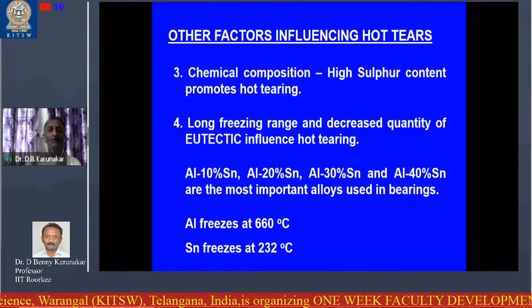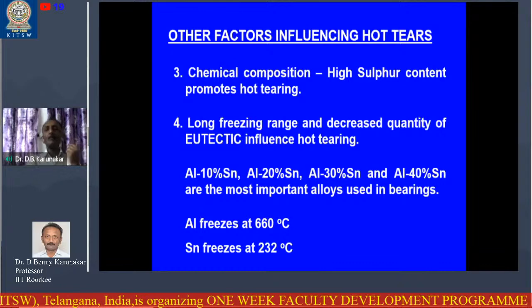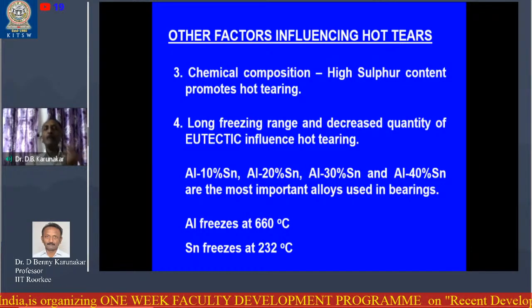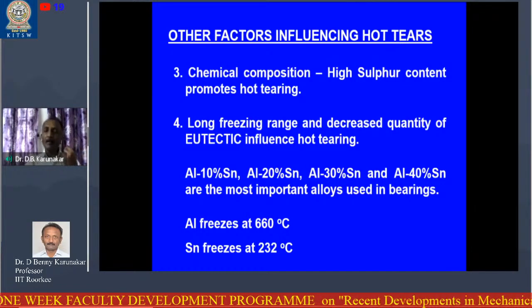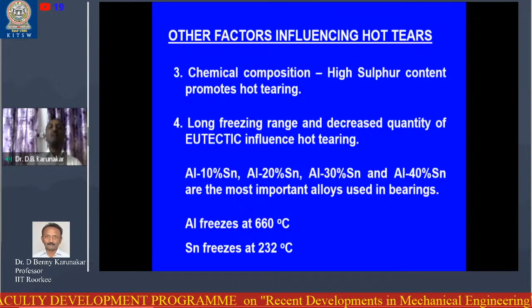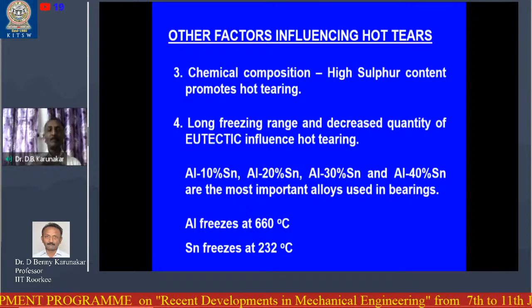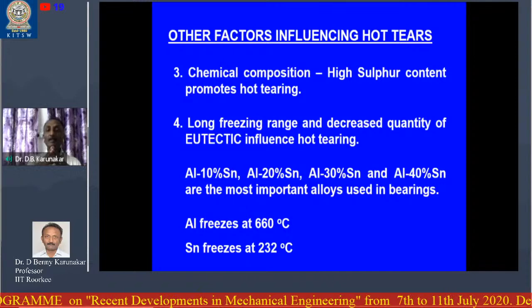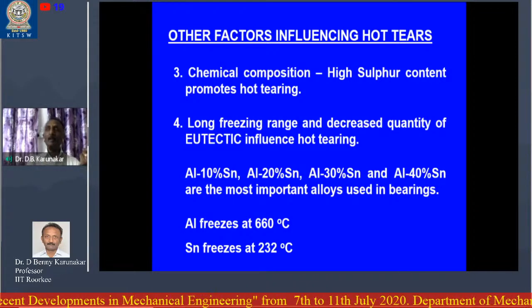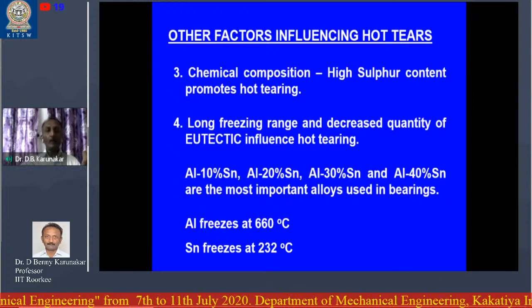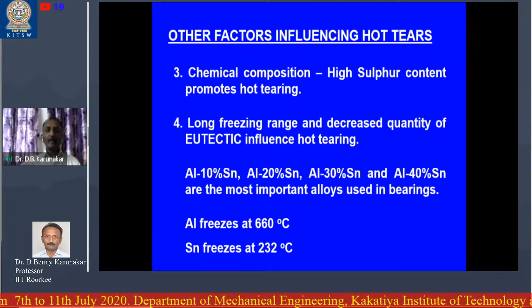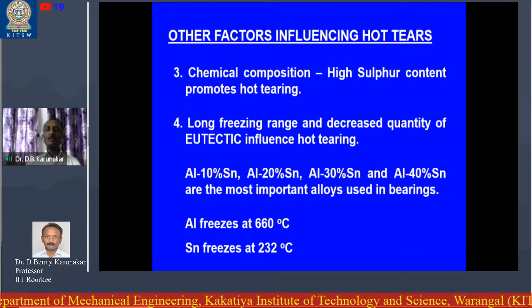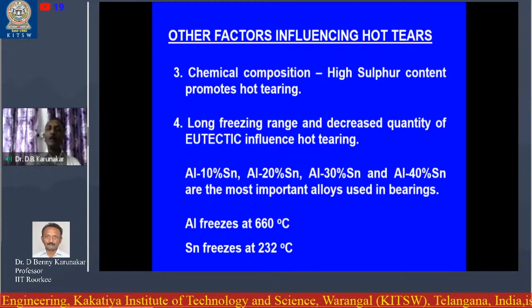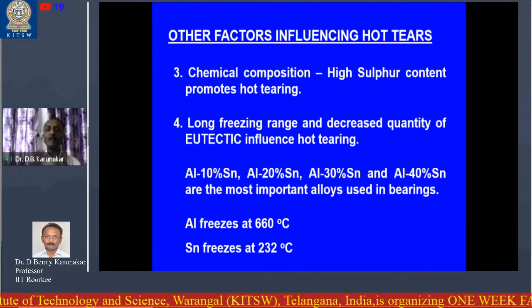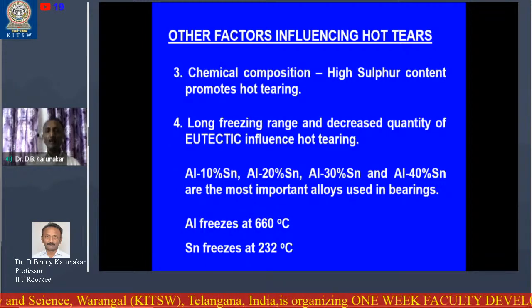When you use this tin in an extremely small amount, maybe 2% or 3%, what will happen? In the initial stage of solidification, yes, there is 2% or 3% of tin, it is in the liquid state, and it goes wherever there is a shortage or contraction, and supplies the liquid metal. But once this 2% or 3% tin is completely consumed, what will happen?